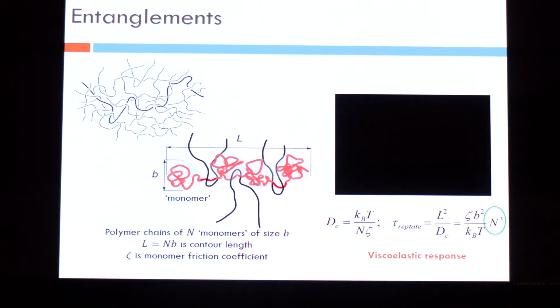And so there is a diffusion coefficient for these polymer chains through these tubes. And let's call that DC. And of course, the longer the tube, the longer the polymer chain, the more friction it will experience, right? So the diffusion coefficient scales inversely as the friction coefficient and the length of the polymer chain.